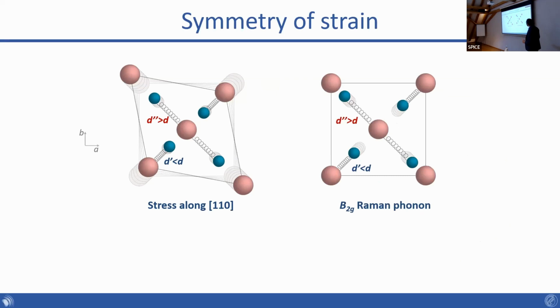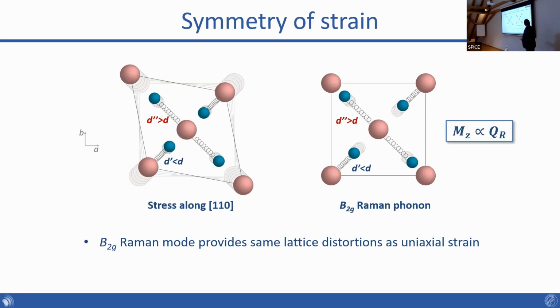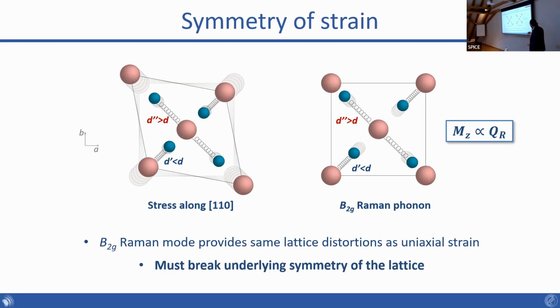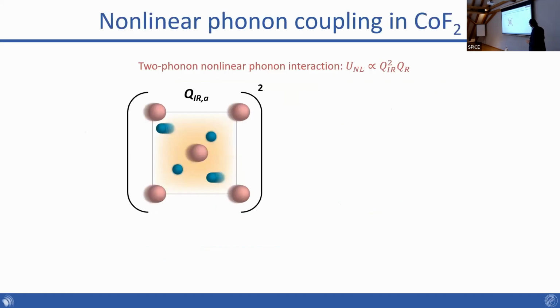And if you look at the atomic motions associated with this phonon, you can see that indeed one of the bond lengths gets shorter, one gets longer, just like with strain, but this is an optical phonon. So you preserve the volume of the unit cell, and you won't be limited by all the elastic constraints that you had before, okay? So in this case, we would expect that if we can displace this Raman mode, we would have a magnetization that is proportional to the displacement. But there's a catch, which is that somehow we need to excite a mode that breaks the underlying symmetry of the lattice. Okay, so how do we do that?